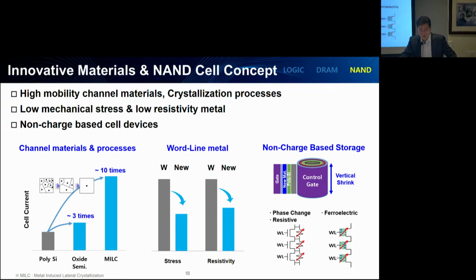On the other hand, in order to improve the mechanical stability, we need low stress and low resistivity metal films without sacrificing the excellent step coverage. And eventually, we may pursue slowing down the total stack height increase. To this end, we need to decrease the operation voltages such as program and erase, currently more than 20 volts, by adopting innovative non-charge-based storage devices such as ferroelectric or resistive memory devices. In summarizing, future flash, innovative cell structures and also the advanced processes and materials for cell transistors and innovative non-charge-based memory devices will enable flash to stack over 1,000 layers and beyond.